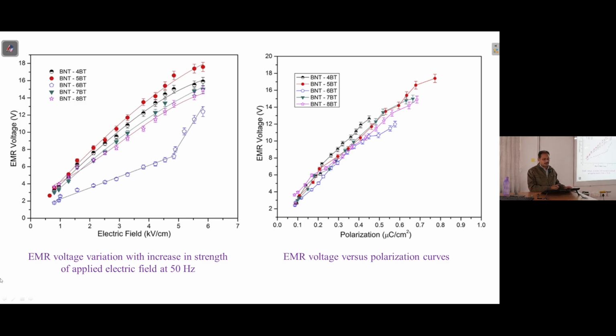So here we can consider this two-phase system, as we had seen that two different kinds of structures are observed, and both exist there. The primary reason for the better performance is that it has a large number of polarization directions. If you have a bulk material, you will have different grains, and all different grains will have a particular lattice structure.